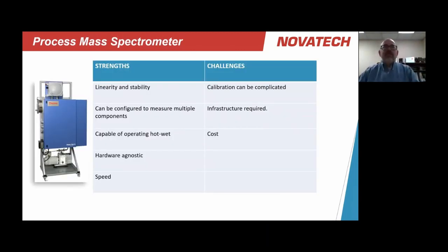So in terms of strengths, linearity and stability, incredibly linear. We can measure from parts per million all the way up to percent levels with the same calibration. It can measure multiple components. It can operate hot, wet. It is hardware agnostic. We don't change the hardware when we want to change the components we want to measure. We simply change the programming and the calibration, which is different than, say, a GC again. And speed, incredibly fast, an analysis in a matter of seconds.